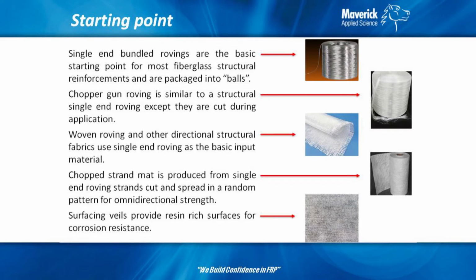Similar to single end roving is chopper gun roving. Chopper gun roving is the same basic thing, it just doesn't have a lot of binder to hold the glass together. So when the pieces of chop are run through a gun and cut into 1.5 inch, give or take, long pieces, those pieces are sprayed in a random pattern. Because there's not much binder holding that string together, you get better coverage. So that's chopper gun roving.